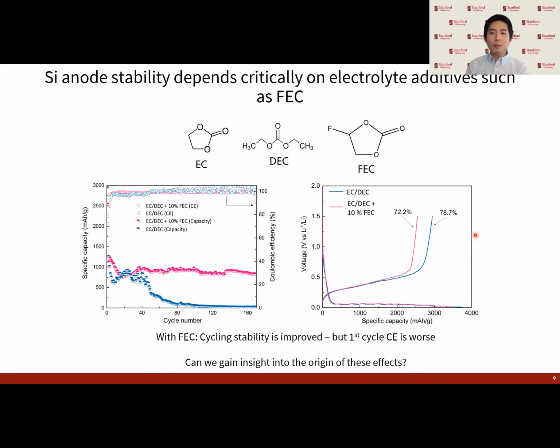With this test platform, we can then start to answer these unsolved questions for the silicon anode. So it's known in the field that the stability of lithium-ion batteries depends very critically on the electrolyte composition. A common electrolyte formulation used in lithium-ion batteries consists of a blend of ethylene carbonate, so a cyclic carbonate, EC, along with a linear carbonate such as diethyl carbonate or DEC. And graphite anodes in this formulation alone, along with a lithium-containing salt, will cycle pretty well.